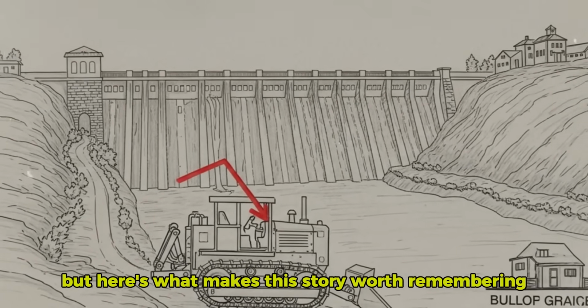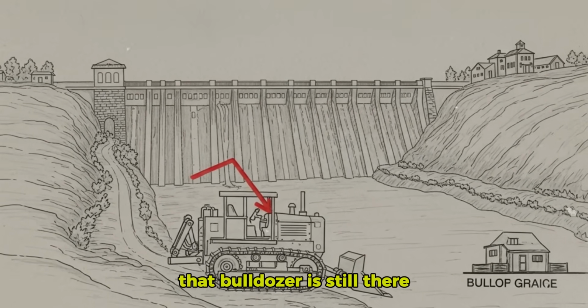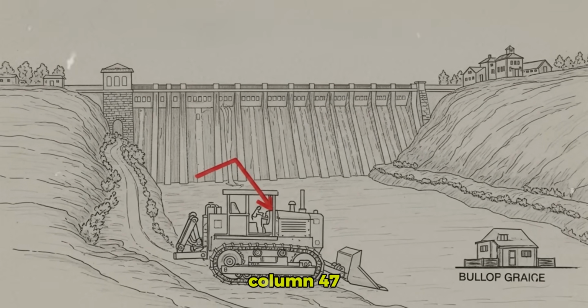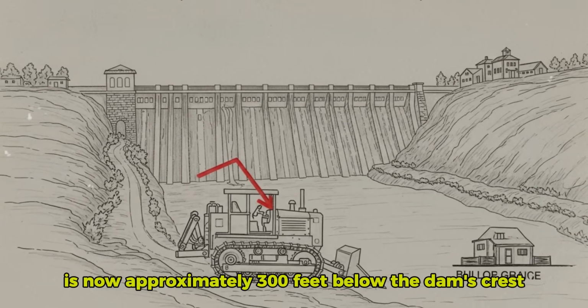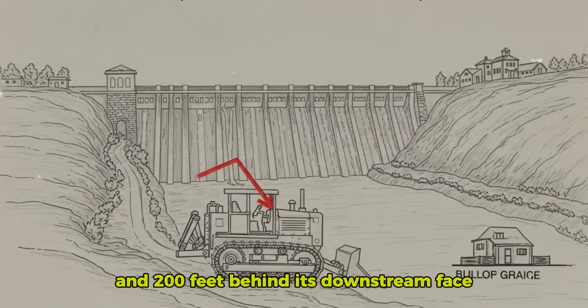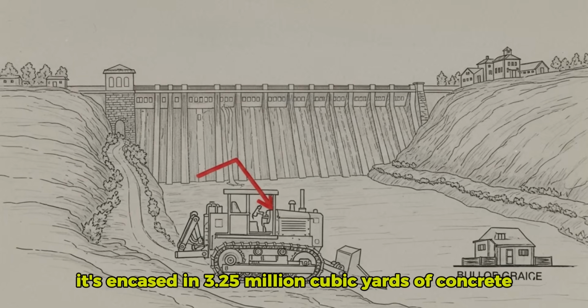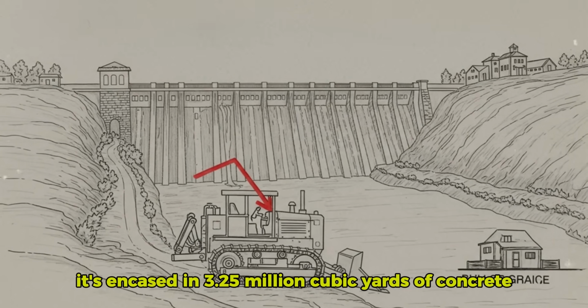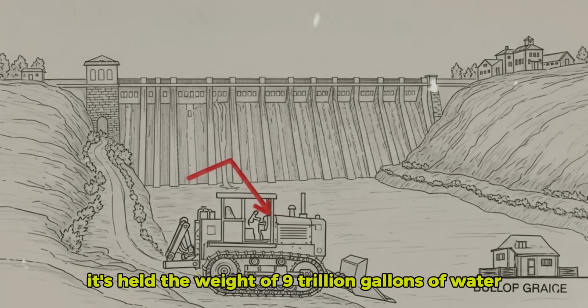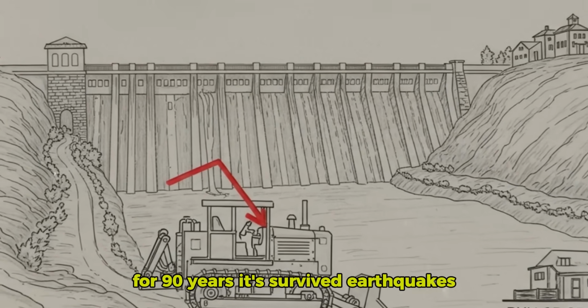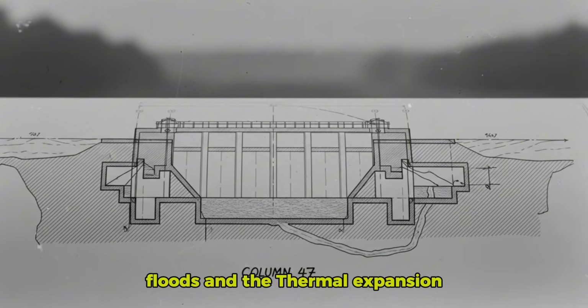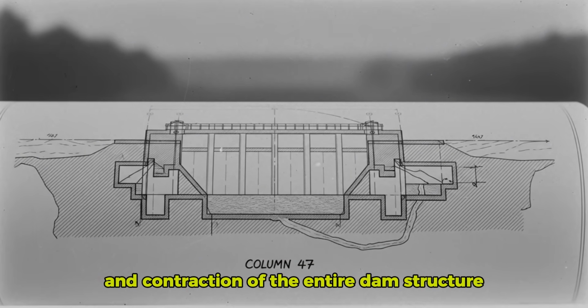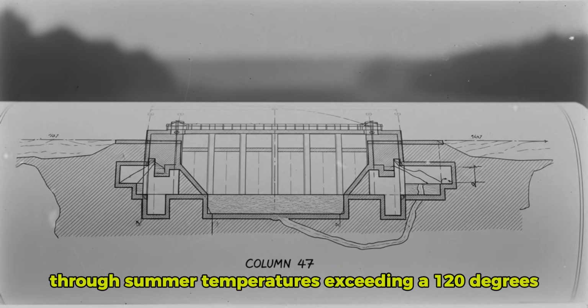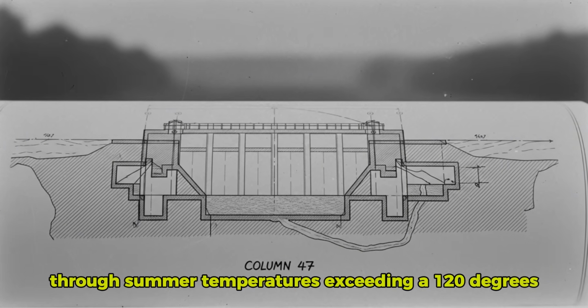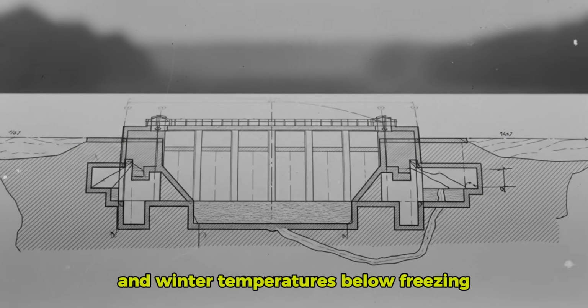But here's what makes this story worth remembering. That bulldozer is still there. Column 47 is now approximately 300 feet below the dam's crest and 200 feet behind its downstream face. It's encased in 3.25 million cubic yards of concrete. It's held the weight of 9 trillion gallons of water for 90 years. It's survived earthquakes, floods, and the thermal expansion and contraction of the entire dam structure through summer temperatures exceeding 120 degrees and winter temperatures below freezing.